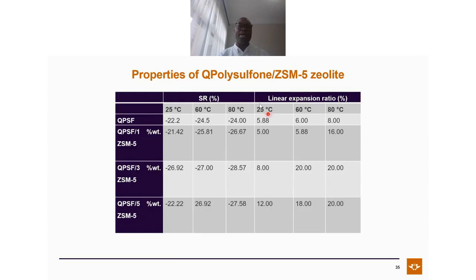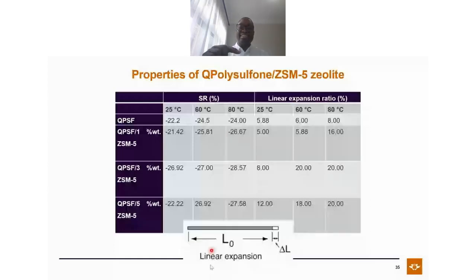Interesting on this one, we expect that if the material absorbs water, for example, if the material was this thick, it absorbs water. It's supposed to be this thick, right? That's what swelling ratio means. If it's this thick, it absorbs water, it becomes this thick, like a tissue. But this material doesn't do that. It has what you call a linear expansion. If it absorbs water, it doesn't increase inside. Actually, it expands linearly. As you can see here, you have a linear expansion. Then instead of the material increasing inside, it actually expands this way.